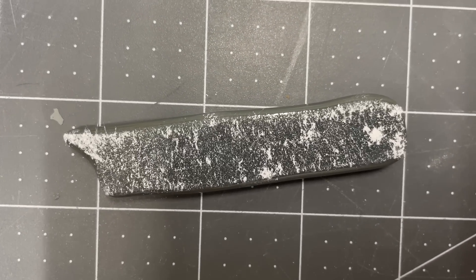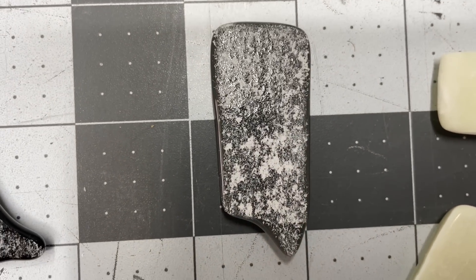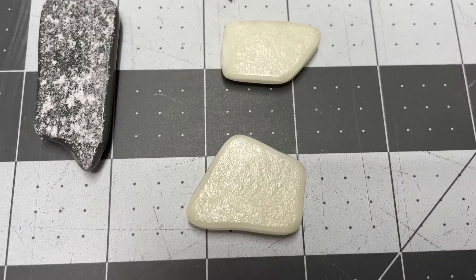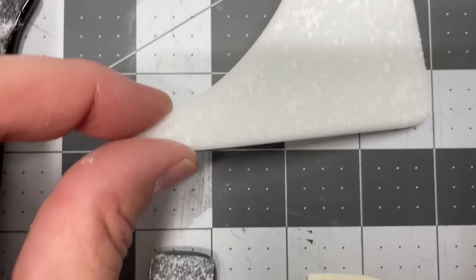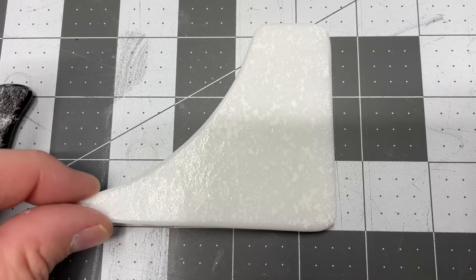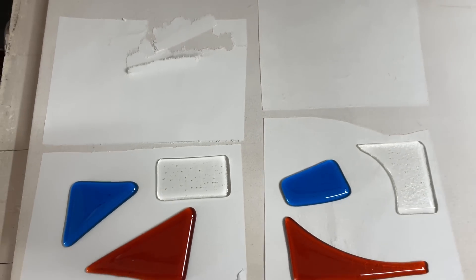The French vanilla came right off. On the gray, there's quite a shine — it picked up a little more paper on the black on the new side compared to the old. The gray on the old actually released surprisingly clean. There's a little more paper stuck to the new, but fairly comparable. On the white, there's some paper but not huge chunks — it did lift off. Looking closely, there might be almost kind of holes there, getting close to the kiln shelf, so definite texture on the new side. The old one is still pretty smooth.